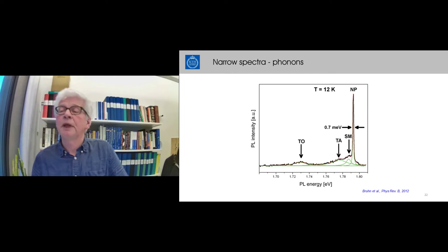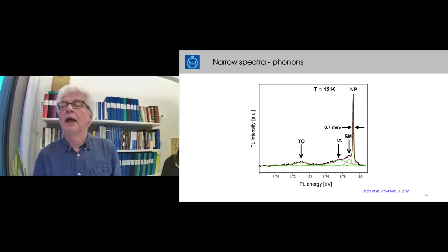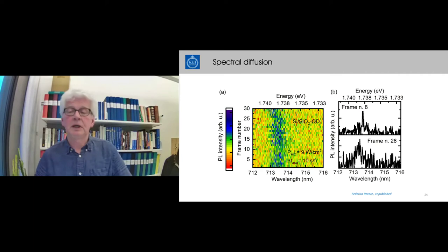Probing luminescence absorption. Of course, in the beginning we had a very broad spectrum, but finally now we have been able to make very good samples and improve our imaging. This was many years ago by now. Here's a typical spectrum from a single silicon quantum dot taken at 12 Kelvin. You see a very sharp peak in the beginning here. We interpret that this is the no-phonon line. Here is probably a TO-phonon line. If you probe several dots, the distance between those two lines is plotted here, which is about 60 millielectron volts, which is known as the TO phonon distance in silicon. Therefore, we can also conclude that, yes, this is really coming from silicon. We also have other features here. And of course, with phonons maybe. And this we interpret as a breathing or stretching mode. So this is the silicon nanocrystal, which is vibrating as a whole like that.